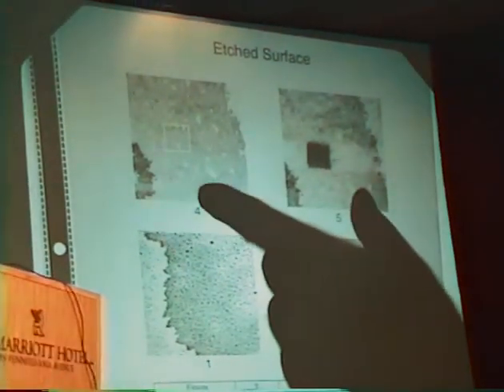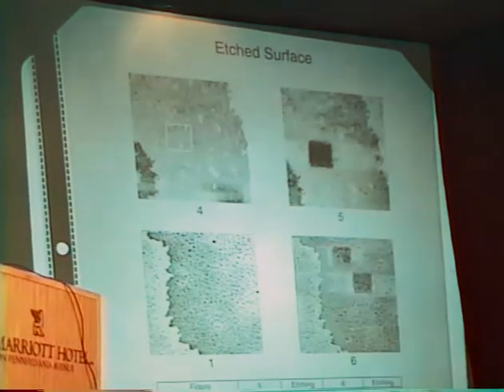Yeah, we actually started in the beginning by transferring films one by one, but after that, we couldn't get to the same area after polymerization. So we developed polycarbonate boxes, which we can put everything in, filled with argon. We put the gold balls covered with molecules in before polymerizing, scan the surface, then polymerize, and then scan again. So it is an oxygen-free environment. We filled that system with argon at least 5 minutes before any experiment.